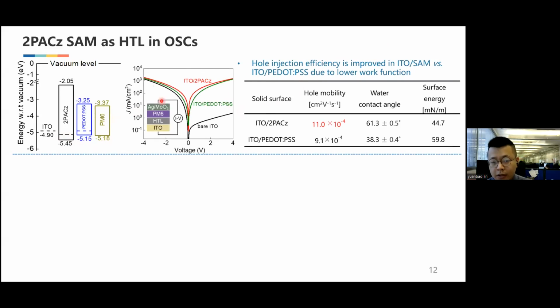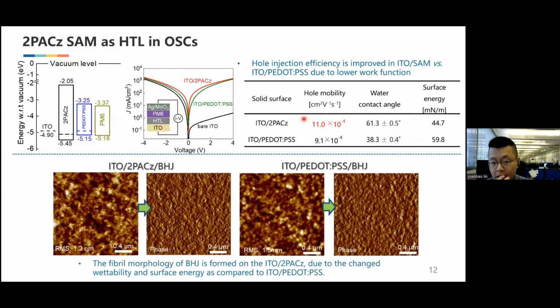When we test the hole-only device, the hole mobility is a little bit enhanced as compared to the PSS. Also, these 2PACz have a different surface energy and wettability as compared to the PSS. When we spin coat the bulk heterojunction on 2PACz, we can see the nanofibrous structure. This nanofibrous structure is better for charge transport, but for the active layer on the PSS, it's very hard to distinguish these nanofibrous structures.